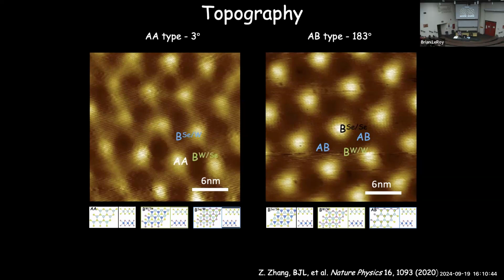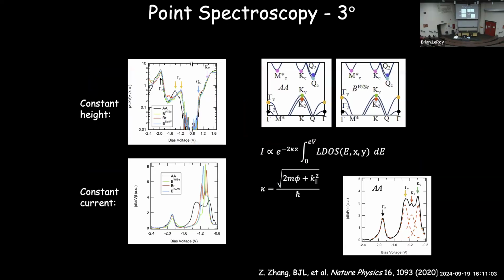And from these images, we can actually identify the stacking configurations. How do the different atoms sit on top of each other here? By taking high resolution images, we can determine what each of these stacking configurations corresponded to. And once we've done that, we can look at the electronic states of these different ones. Let me just look at this 3-degree twist angle one.